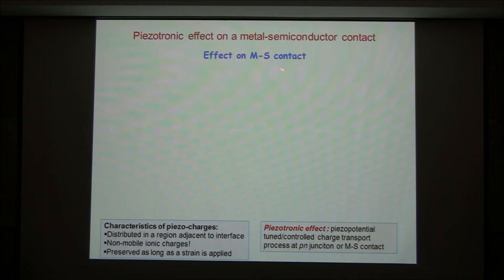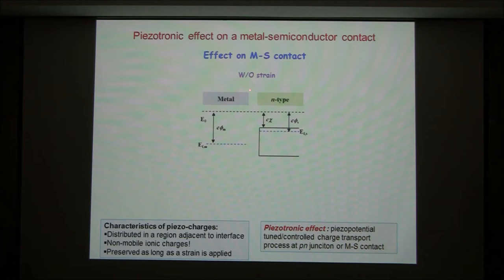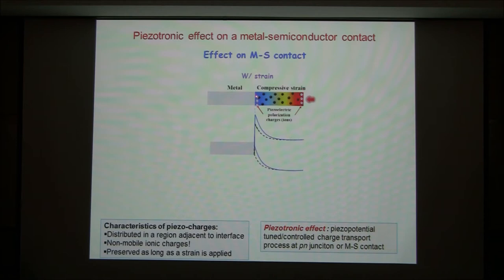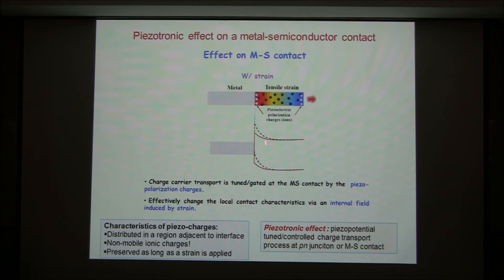Let's look at a simple analogy. We have a metal-semiconductor contact. When the interface forms, we can form a Schottky contact. With the Schottky contact, we have a barrier. If this side is piezoelectric and semiconducting, under mechanical strain, polar charge is created. Negative ions raise the barrier. If you reverse the strain, positive ions at the interface lower the barrier. This raised or lowered barrier at the interface can gigantically change the transport of charge across the interface.